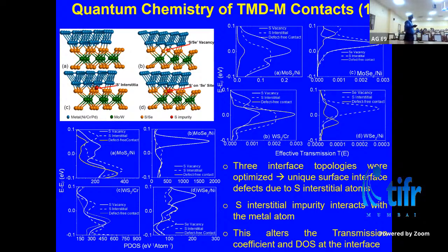So what is this? This is pristine, where you have a TMD and you have metal. In this case, we have either a sulfur or selenium vacancy created. In this case, we have a sulfur interstitial introduced, and in this case, we have a sulfur interstitial at a selenium vacancy site. So these are the various scenarios that we studied, and they can be realized experimentally, which I'll talk about later.